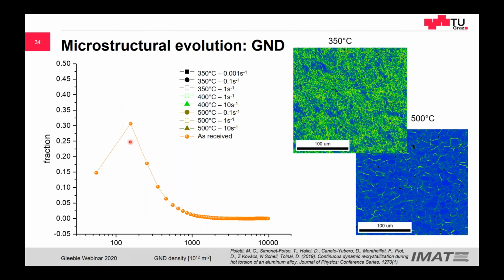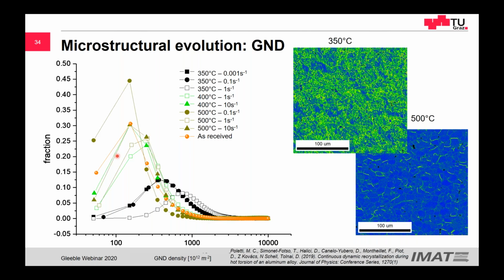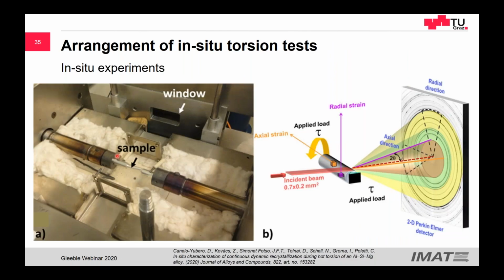So in the as-received condition, we have this distribution of dislocations. If we deform at low temperatures, we produce a large amount of substructure. And if we deform at higher temperatures, then we will have much fewer dislocations, which means a much higher amount of recrystallized material. We did the same at the in situ synchrotron. We thought, okay, we bring what we understand into the synchrotron and try to measure the change in the texture and the change in the dislocation density during hot torsion.